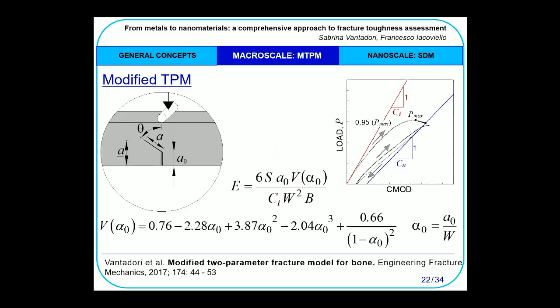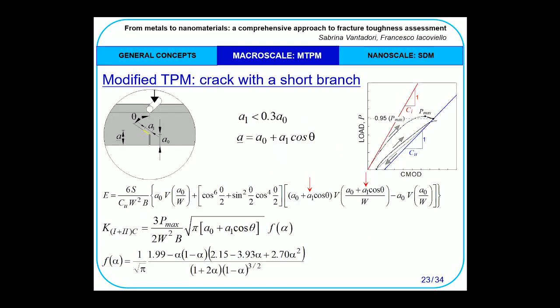A modified procedure is proposed, assuming a kinked crack with one branch characterized by an orientation theta. The elastic modulus is calculated as previously discussed, while for the effective critical crack length calculation it is needed to distinguish between the case of a crack with a short branch and that of a crack with a long branch, since the energy release rate changes accordingly. The boundary between these two cases is represented by the ratio a1 over a0 equal to 0.3.